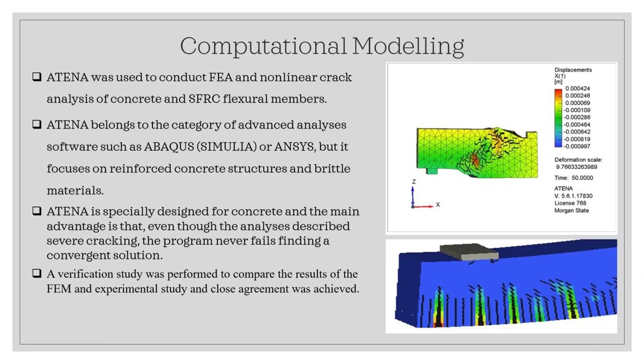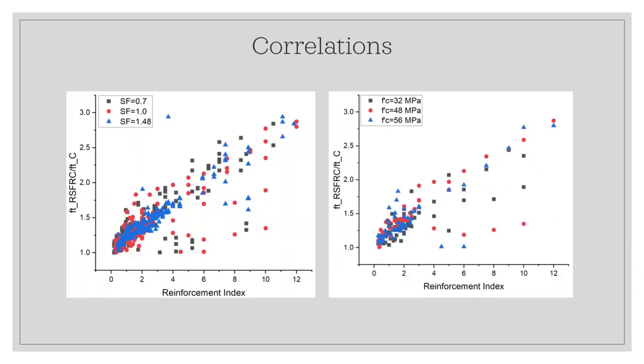As a result of that, we did lots of studies trying to see the correlation between different design parameters and tensile strength. And these plots are showing the different reinforcement index. The parametric study conducted in this research was based on more than 500 different scenarios with all different parameters, within the ranges that I mentioned previously. We try to see the correlation between reinforcement index and the ratio between tensile strength of recycled steel fiber reinforced concrete and tensile strength of regular concrete without fibers. And here you see the results. So these results were set for different shape factors: 0.7, 1, and 1.48.